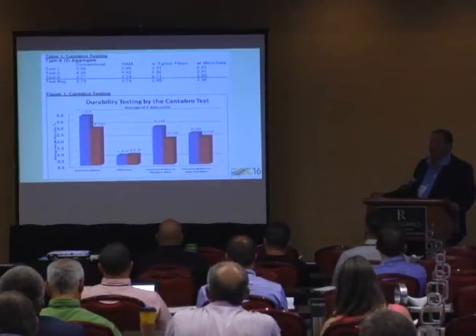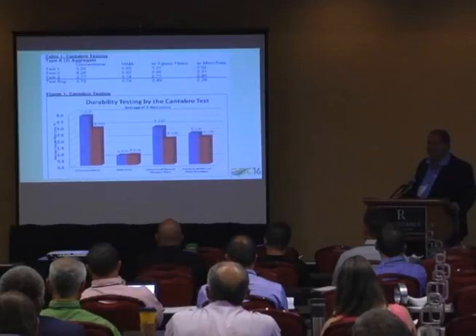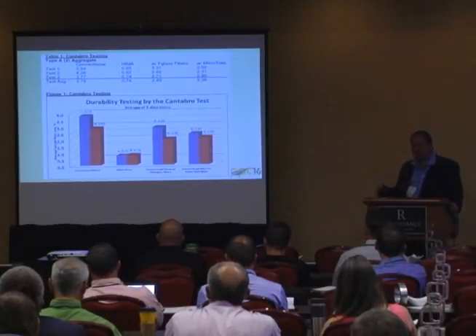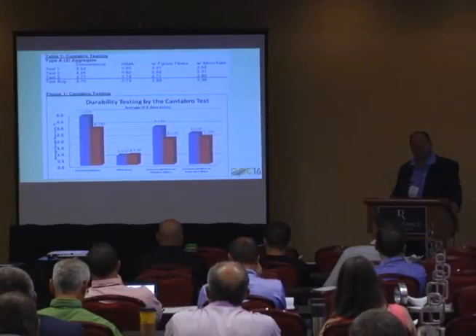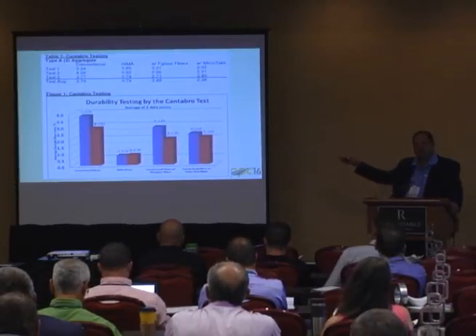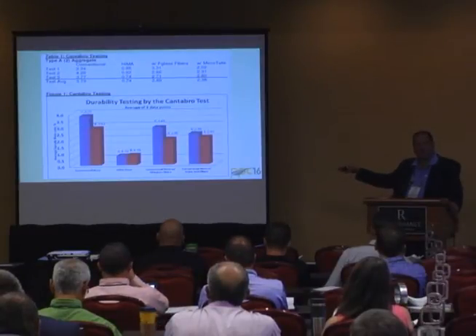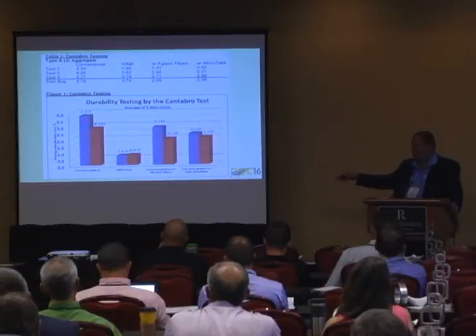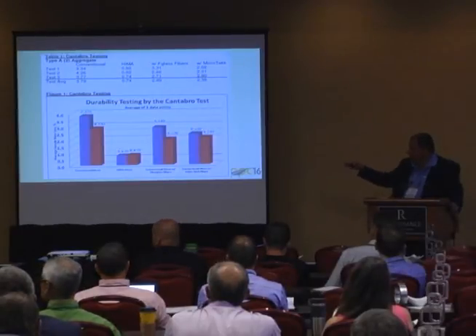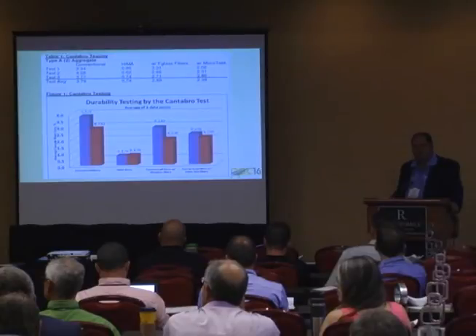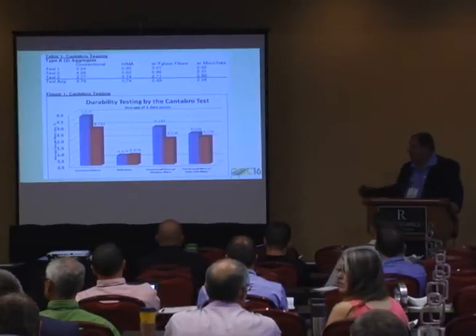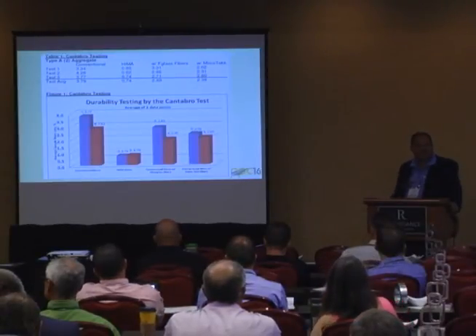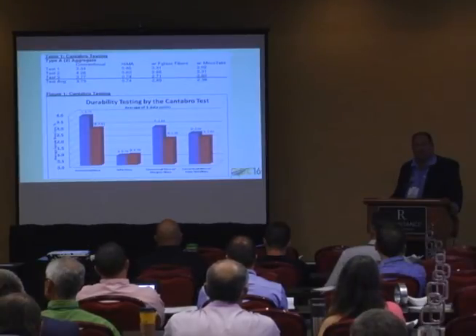So here's those Cantabro results in a graphical presentation. And if we go up there today, and I've gone back there, it's a good test section. We had 2 different machines, so we might have had some equipment issues, but what this result tells us is what we're mimicking in the field. We are seeing one that's performing much better, the high mod. The other polymers or the fibers are performing very well, and the traditional micro is performing as expected. But we are seeing some differences.